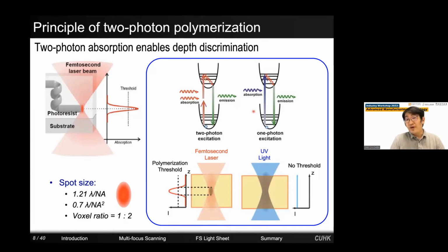In comparison with a conventional stereolithography process, the 2-photon process has depth discrimination. In other words, it only polymerizes material within the focal point that's much smaller than a size of 1 cubic micron. And it is also very sensitive to a polymerization threshold. So in other words, if you finely control the laser power, you can write structures much smaller than the diffraction limit. And that's why much smaller features than the wavelength of light can be created.